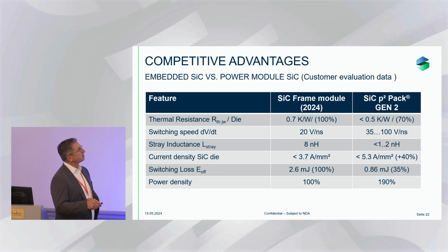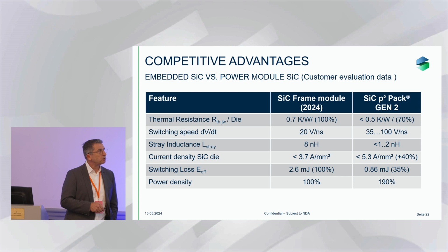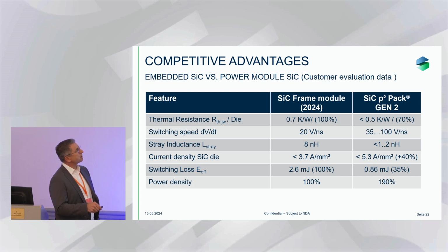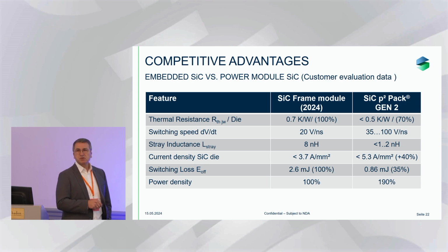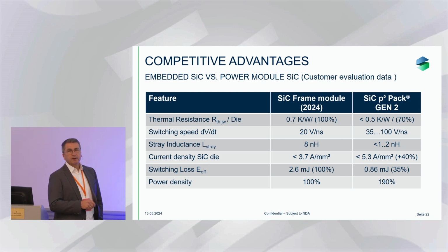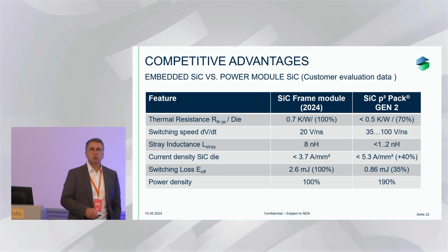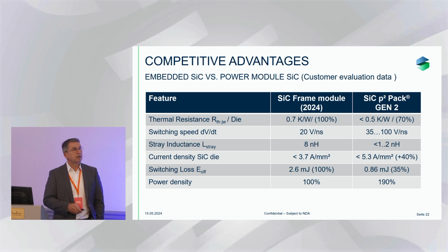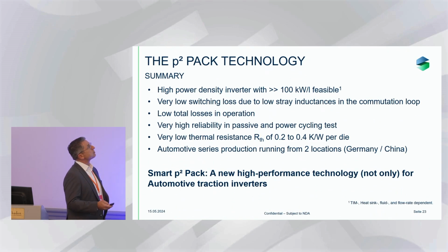A very interesting figure is this one. The current density that you can drive across the component was limited to 3.7 amps per square millimeter in the module, but 5.3 amps per square millimeter device surface area, which is 40% more in the embedded. This is coming from creating less losses and dissipating it better than a module does. So in terms of power density, if you put the module to 100%, our customer achieved 190% power density with the embedding construction. So this brings me to the summary.